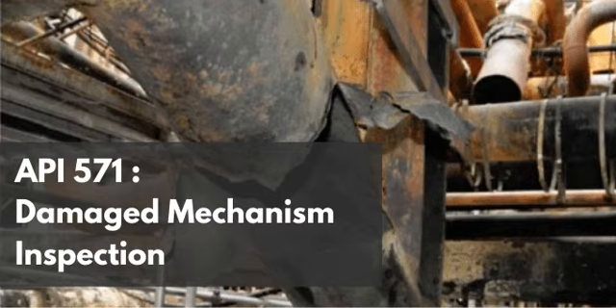If a ferritic 400 series stainless steel is absolutely required for process corrosion reasons, engineers must purposely select the lower chromium alloys, as we talked about earlier. Exactly. They must specify 405, 409, 410, or 410S, which the text explicitly guarantees are significantly less susceptible to the aggressive phase separation. Okay, that makes sense.